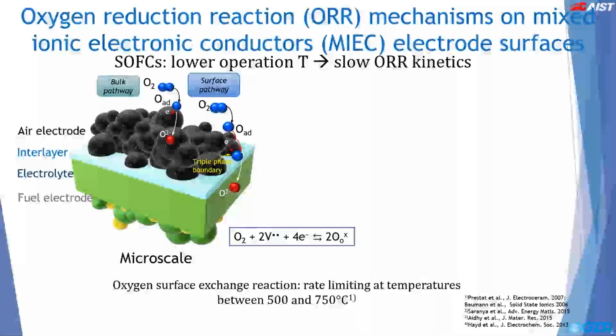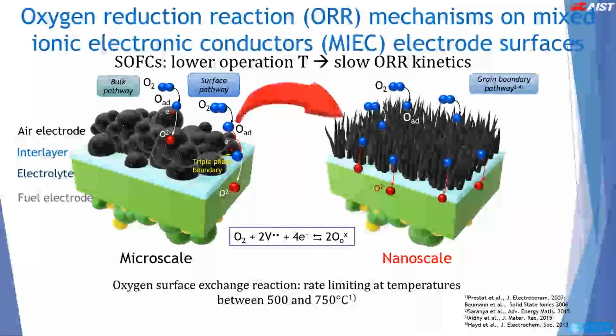Conventional microstructures, on the other hand, are also comprised of microscale grains, typically prepared using wet processing methods like screen printing. This means that the density of triple phase boundaries is limited by the size of the grains. On the other hand, using thin film deposition, it is possible to tune the microstructures in the nanoscale level, which means that the grains can be grown with much smaller dimensions and possessing a much higher density of triple phase boundaries as well as grain boundaries.